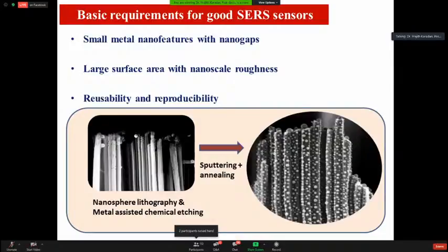By employing all these basic requirements, we have fabricated silver nanoparticle decorated silicon nanopillars. This is our sensor, and these silicon nanopillars were fabricated by nanosphere lithography and metal-assisted chemical etching, followed by sputtering of silver film and annealing at 400 degrees Celsius for 5 hours to get a typical sensor.